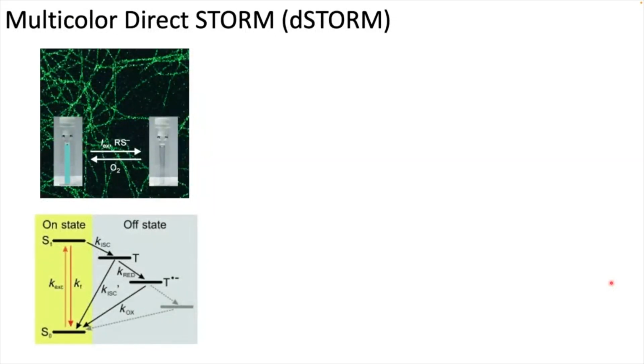We can also do it with organic dyes. The method most used to do super resolution localization microscopy with organic dyes is called dSTORM. The whole idea with dSTORM is that you add into your solution a buffer that contains a reducing agent and an oxygen scavenger system, so that you reduce the concentration of oxygen. Usually you have your molecule, you are irradiating it, and it goes between the singlet ground state and the excited state. Eventually, some molecules will end up in the triplet state. What this special buffer does is that it offers an alternative pathway for the molecule in the triplet state that makes it go back to the singlet ground state with a higher probability. Because it induces this alternative route, the molecule can blink on and off several times before it's completely bleached.